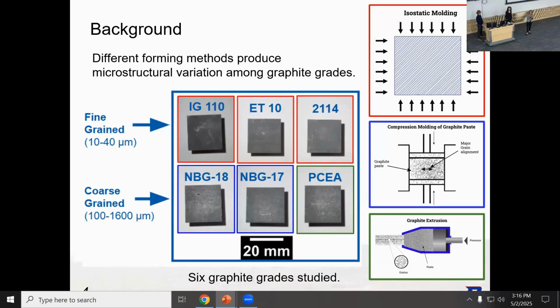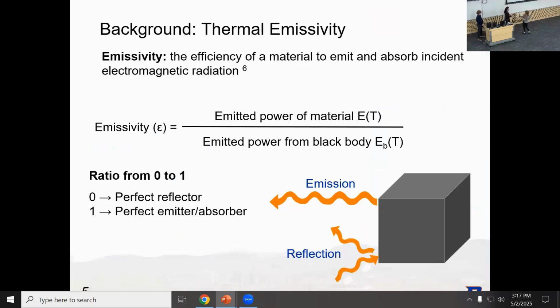And we hypothesized that the more coarse grain graphite would result in higher emissivity due to increases in porosity, which would increase the surface area for higher emissivity. Now, the other area we were interested in was oxidation. Inside the nuclear reactor core, there can sometimes be minor air ingress, which, because high-temperature gas-cooled reactors are operating up to 1,000 degrees Celsius, will oxidize the graphite, and so we want to have some insight into how that will impact the emissivity.